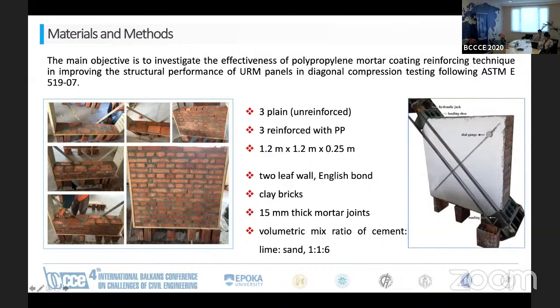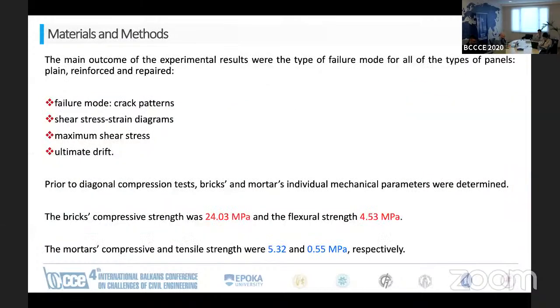Then these walls were tested in diagonal compression, either unreinforced or reinforced, in groups of three. And the main outcome of the experimental result was the type of failure mode for all the panels. Then we identified the main crack pattern, we identified the shear stress and strain diagram, and we could measure the maximum shear stress and the ultimate drift.